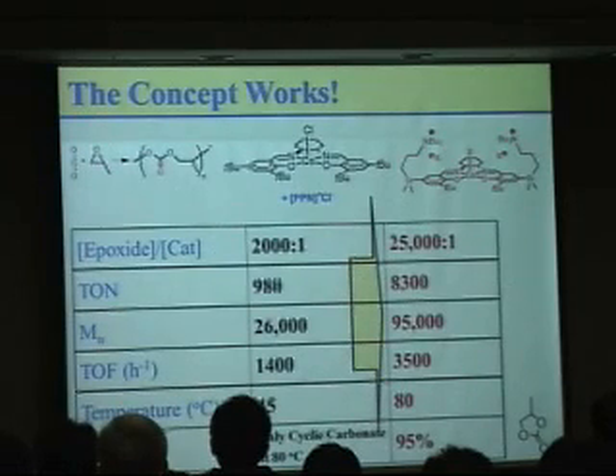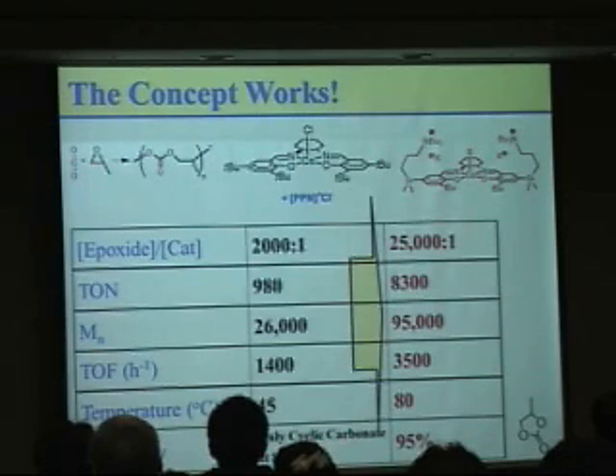And my concept works, so I can see it. By connecting the two components using the flexible linker, it shows activity at very low catalyst concentration, epoxide to catalyst ratio 25,000 to 1. At this condition, by obtaining a thick viscous polymer solution, we increased the turnover number almost 10 times. Because of the high turnover number, we can obtain high molecular weight polymer. Turnover frequency was also doubled.